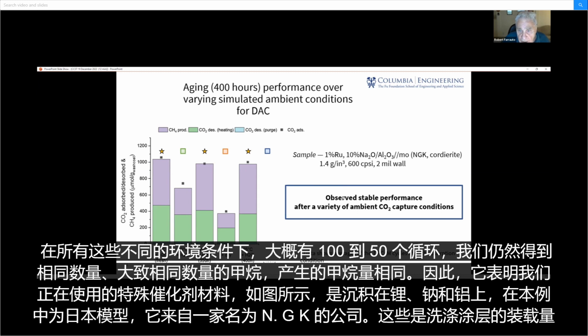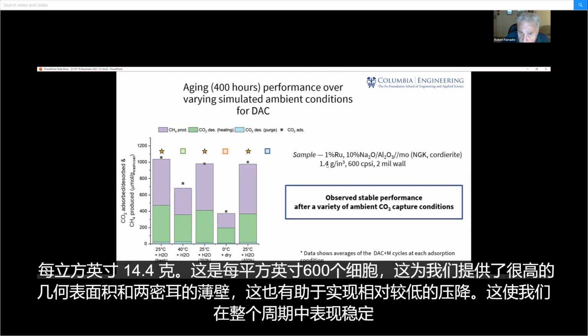So it shows that the particular catalyst material that we're using, which is shown here, is ruthenium sodium alumina, which is deposited on, in this case, a Japanese monolith from a company called NGK. And this is the wash coat loading, 1.4 grams per cubic inch. It's a 600 cell per square inch, which gives us that high geometric surface area, and a thin wall of 2 mil, which also helps contribute to relatively low pressure drop. And that gave us, over this whole cycle, stable performance.